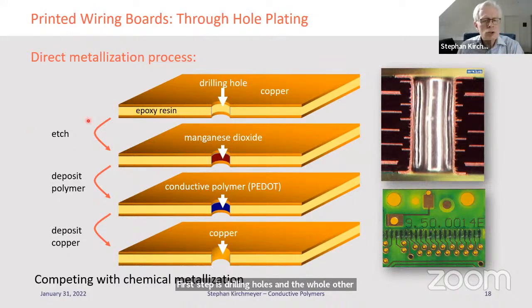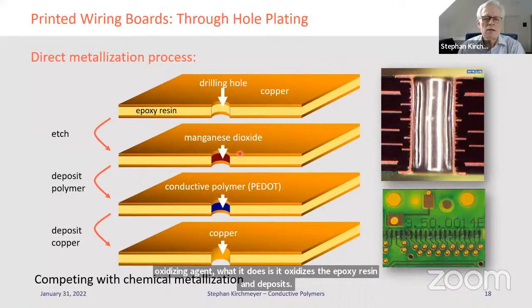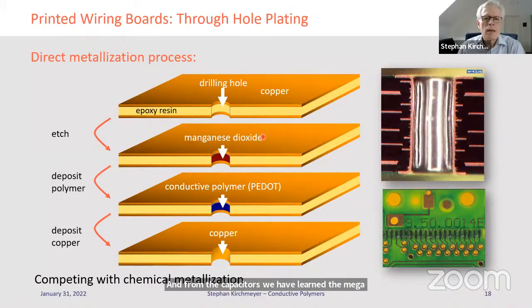There's an etch which is done with potassium permanganate, and this is a strong oxidizing agent. What it does is it oxidizes the epoxy resin and deposits a small layer of manganese dioxide. And from the capacitors, we have learned the manganese dioxide, first of all, has a little bit of conductivity, which is not so important, but on the other hand, is also an oxidizing agent.